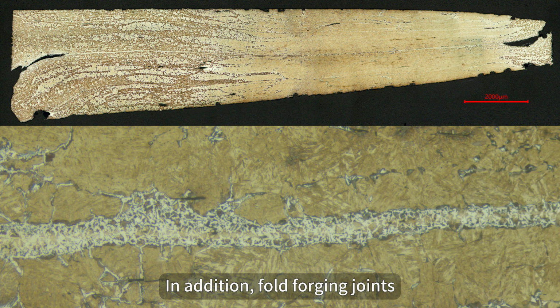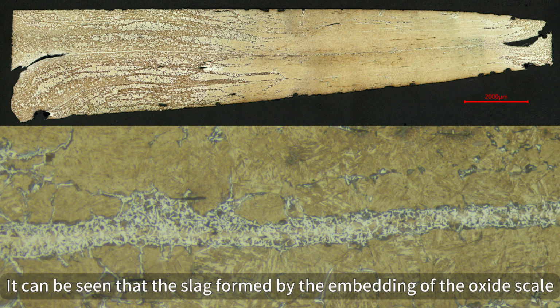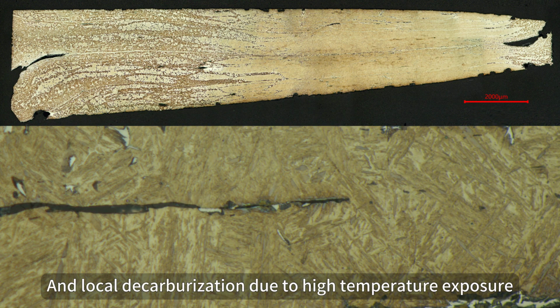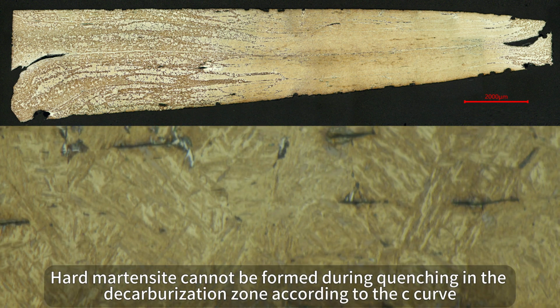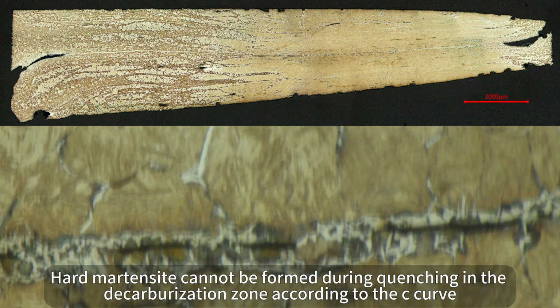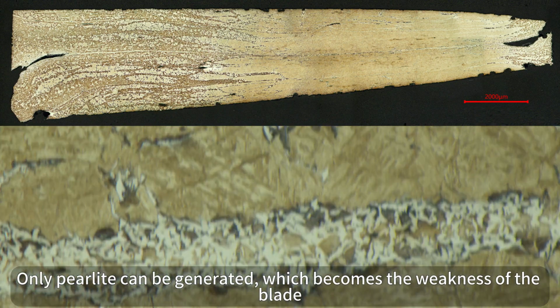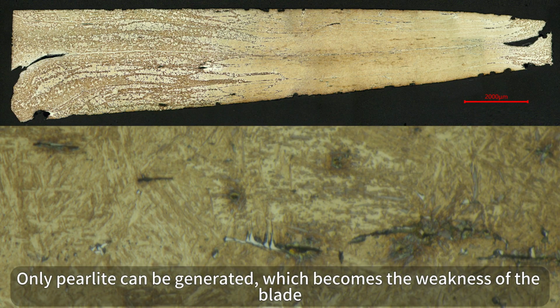In addition, at the fold forging joints, it can be seen that the slag formed by the embedding of the oxide scale and local decarburization due to high temperature exposure. Hard martensite cannot be formed during quenching in the decarburization zone according to the C-curve. Only pearlite can be generated, which becomes the weakness of the blade.